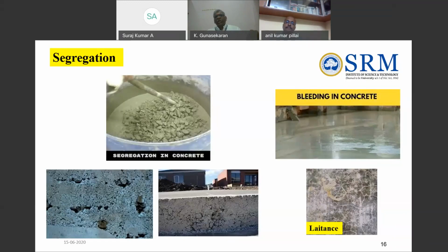Also, once the concrete surface is finished and people see the thin water film over there, they go for troweling or floating over the surface. In that case, the coarse aggregate goes down and the cement and water come up to the top. They will not realize what is happening by that time. This formation of cement paste at the surface is called laitance. You can see the figure here. This is not a crack formed in the surface of your concrete. It is because of laitance, the thin layer of cement paste caused by bleeding.